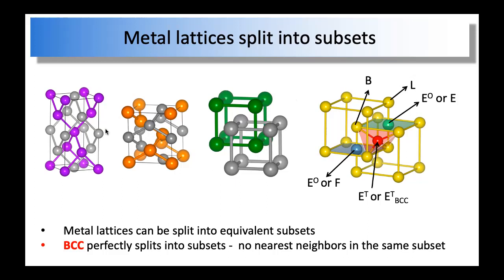And also, comparing with FCC and HCP, the split of the BCC lattice is perfect in the sense that every atom in one subset has only atoms from the other subset as neighbors in the original BCC. So for example, this atom belongs to this sublattice, but its nearest neighbors are all atoms of another sublattice or subset. We tend to use the word subsets because sublattice seems to have a very special meaning. So in that sense, BCC is indeed special compared with FCC and HCP. For FCC and HCP, you can never find this perfect split.